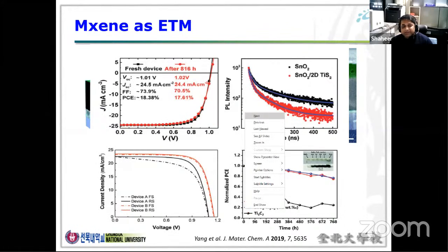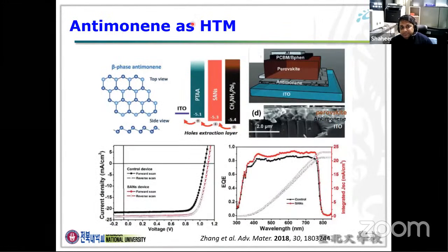Then another material, antimonene: with simple grinding, we make a layered structure, so we can also use it as a hole transporting material. We can insert a very thin layer, less than 50 nanometers, and design the inverted structure like this one. It also shows very good performance, over 20%. The good thing is that using antimonene does not show any hysteresis between forward and reverse scanning.